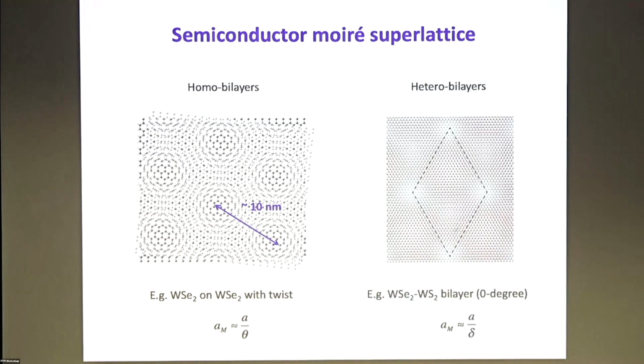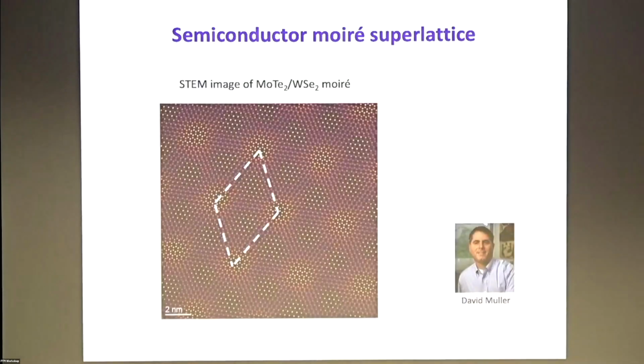Different from graphene, you can also use two different materials without any twist angle, but make use of the lattice mismatch between the two materials to produce a moiré pattern. For instance, this particular combination aligned at 0 degree, tungsten selenide and tungsten sulfide, has 4% lattice mismatch, and that will also produce a moiré pattern with period about 10 nanometers. So compared to graphene, there's an extra way of producing the moiré lattice.